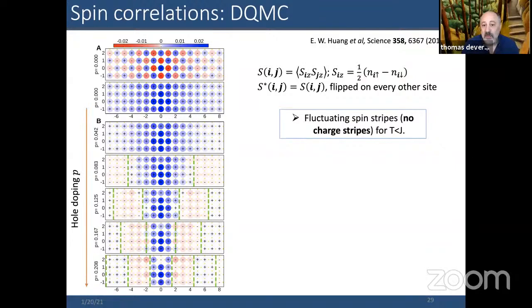So going to finite temperatures then, into quantum Monte Carlo, one can look at similar evidence for stripes. This is looking at SiSj, the spin-spin correlation function. You can see up here in the upper right-hand corner at half filling, it's plus minus going along from the reference spot here at zero, meaning it's an antiferromagnet with some finite correlation length because we're at elevated temperatures. And if we plot the sublattice magnetization, just flipping the spin at every other site, then you just have a nice uniform-phase antiferromagnet.